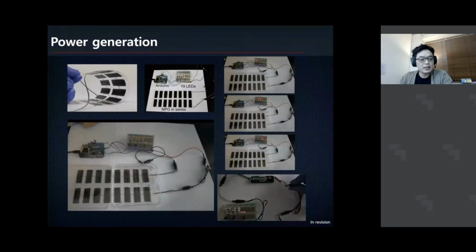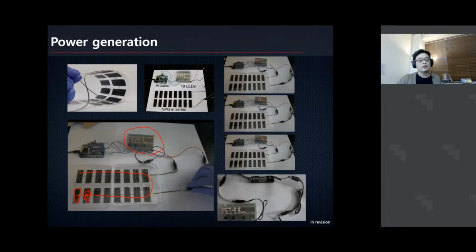We connected 16 cells. Each of these is a graphene oxide film. Here in the half, you put the high concentration, here the low concentration of sodium chloride, and connected in series. Okay, so that's the sort of performance you can get out of those energy generation systems. As a comparison, once again, I attached the AA commercial battery, and those are the intensity of light lit up.